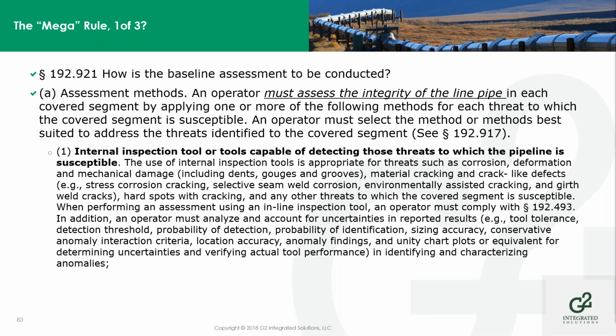921 talks about a baseline assessment. An operator must assess the integrity of the line pipe at each covered segment, using the internal inspection tool or tools capable of detecting those threats. Right, an operator must select a method or methods best suited to address the threats identified. So the use of internal inspection tools is appropriate for threats such as corrosion, deformation, mechanical damage, cracking, crack-like defects, and hard spots to which the covered segment is susceptible.